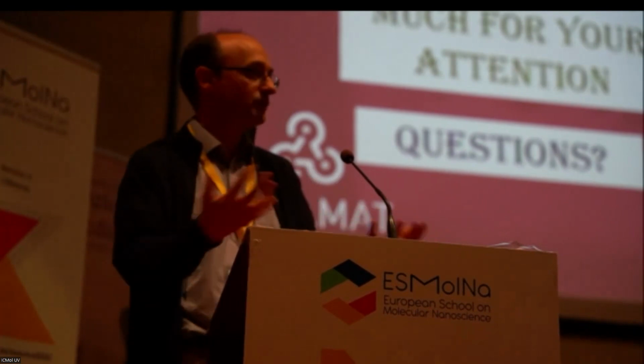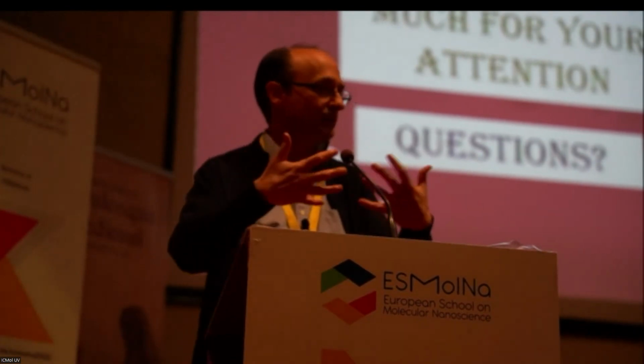Yeah, thank you. It's a very good question. With the technology we are using, which is basically a combination of the polymer and the gas, it's really important to have a very high solubility. That is the key parameter. So if you try to use polyethylene, for instance, you will need a gas with a high solubility in polyethylene. So you need to find the right combination. PMMA plus CO2 is very nice because solubility is very high, and then you can reach this kind of structure. If the solubility is not high enough, then it's very difficult to reach these very small cells in the material. So it's about trying to find the right combination for every system.